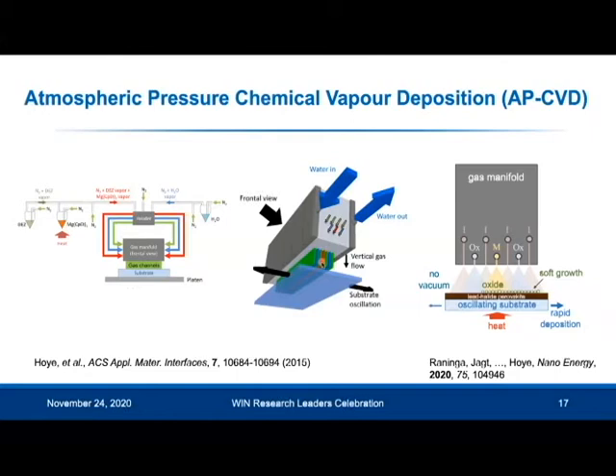This is spatial ALD. What I tend to do is have a large spacing between the bottom of the manifold and the substrate, so that there's mixing of these precursors in the gas phase. So we get CVD rather than ALD growth. And what I found is that this gives very similar properties to ALD films. So the oxides are pinhole free, they're uniform over the deposition area, and also they're conformal onto high aspect ratio nanostructures. So I get the benefits of ALD, but I also get the benefit of the fact that with CVD, I get a much higher growth rate.